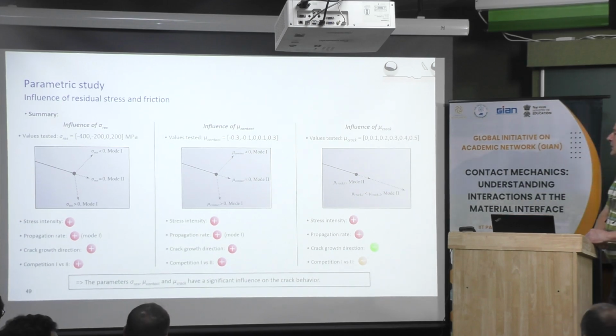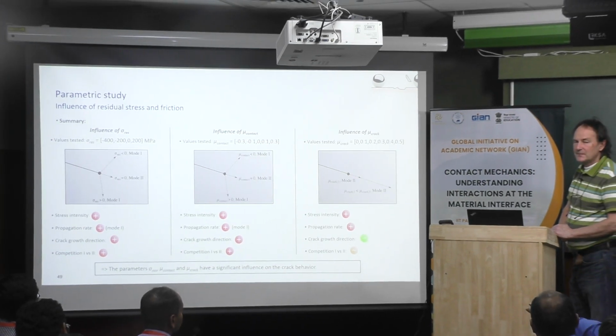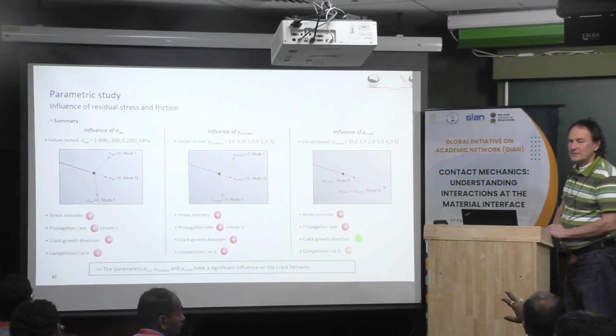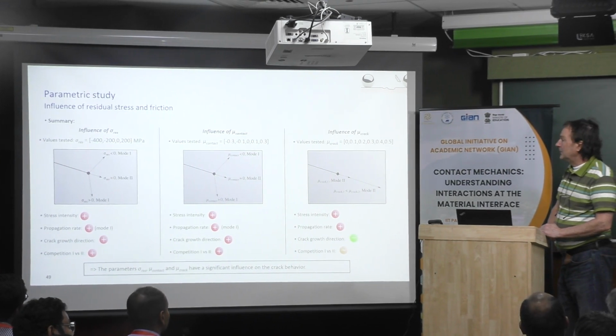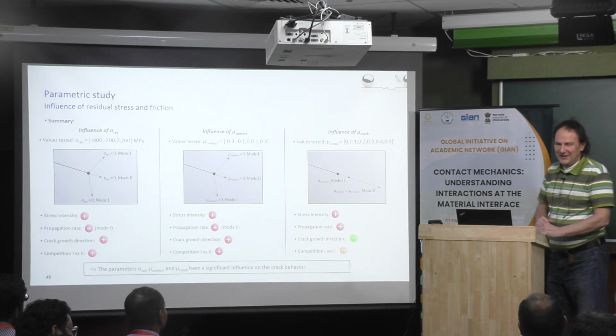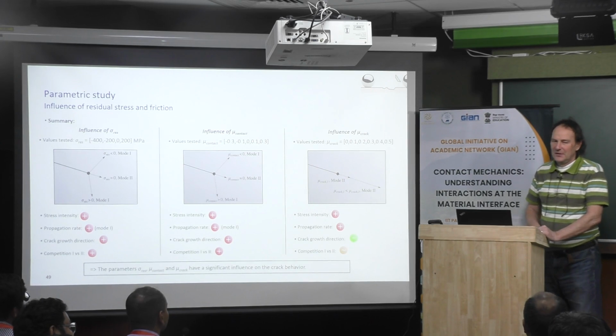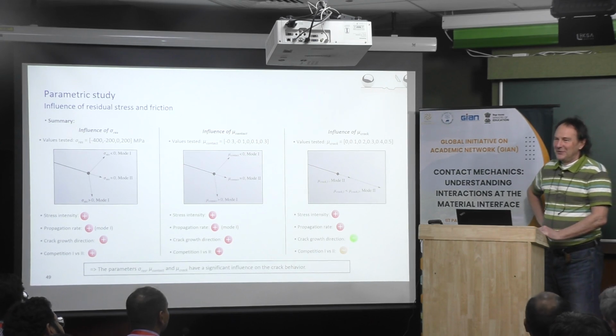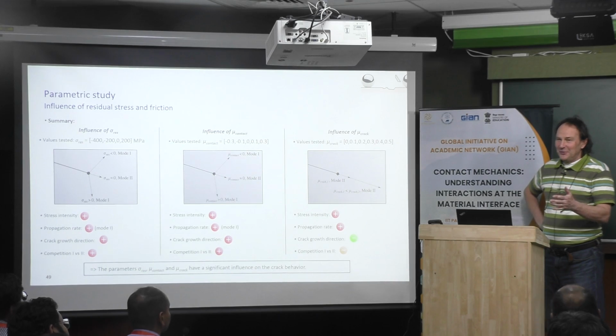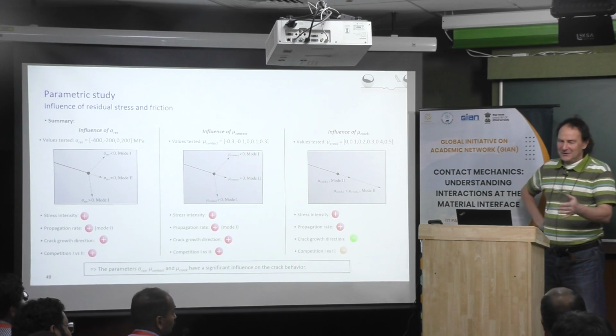Mu for crack. So mu crack 1 is less than mu crack 2, then we will go for this. Yes, it is correct. What I feel is if it is mu crack 2, so we are considering if any other crack is there, if that friction will be higher, it will not go to that side, it will keep on going to where friction is less. Yes, that is correct. My point is, how can we measure the mu for crack? We cannot measure mu. So we are simply predicting it is 0.1, 0.2, 0.3, it cannot be measured. Yes. In fact, when you do a model, you give a number for the friction coefficient. I think there is no other way.